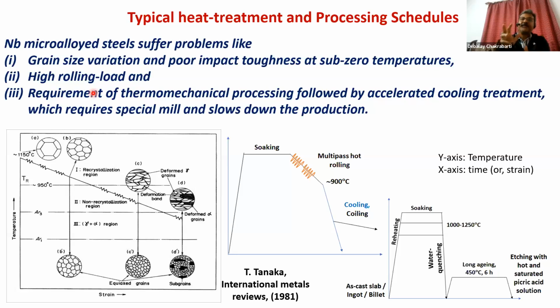Second, there is something called rolling load, because the steel has to be rolled in an industry and the mill has to be capable of rolling the steel to the particular size. So the rolling of these niobium kind of steels is more complex, because not only does it require higher rolling load, but also some very controlled rolling facility. That means you have to roll, then hold for some time, and roll again. So that can hamper the productivity as well. So this is the second point.